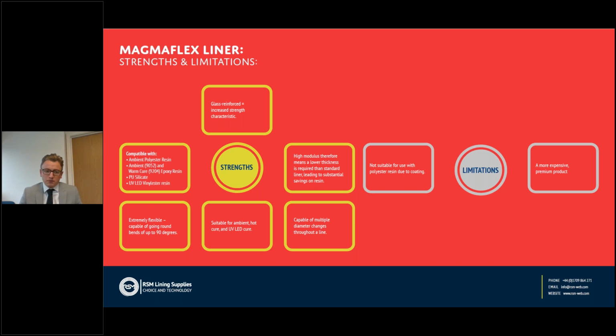Other strengths is that it's extremely flexible to go around 90-degree bends, and it can also do diameter changes throughout a line. The limitations of this product is that it's not suitable for use with polyester resin due to the coating. You will see the same issues with MagmaFlex as you do with Echo Liner. And it is a more expensive premium product because of what it offers you in diameter change, in flexibility, and in strength.